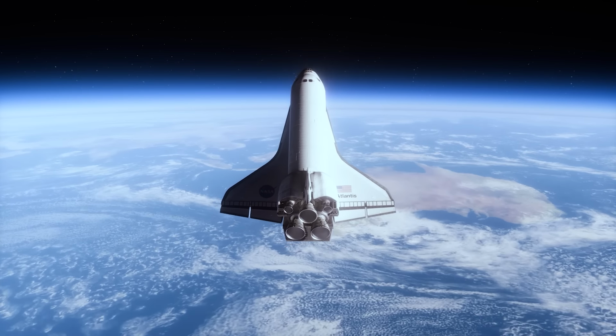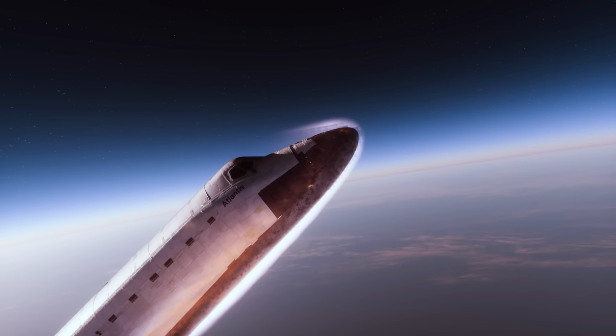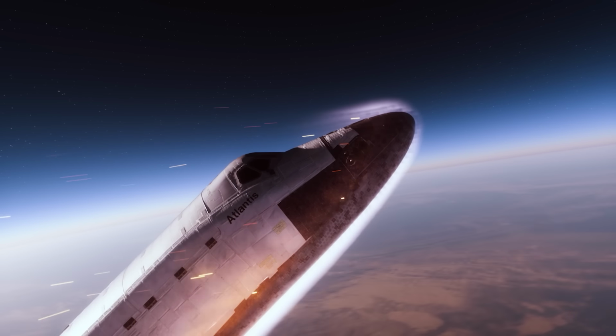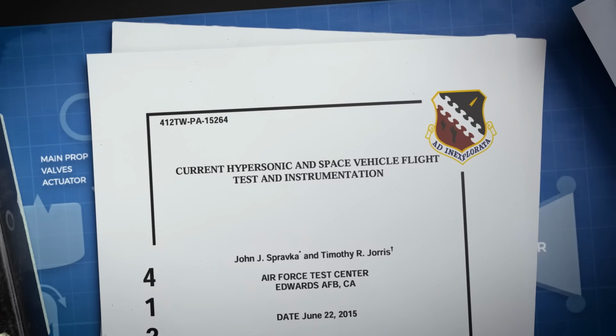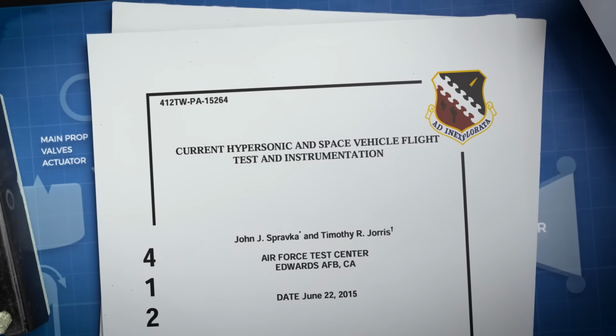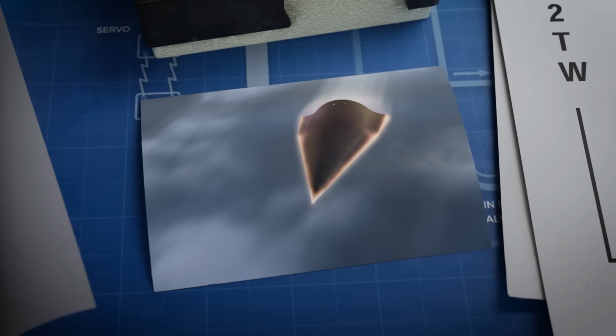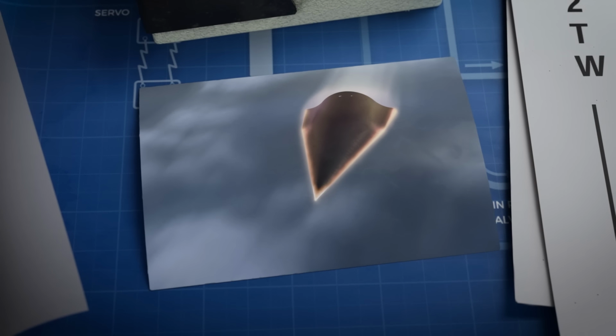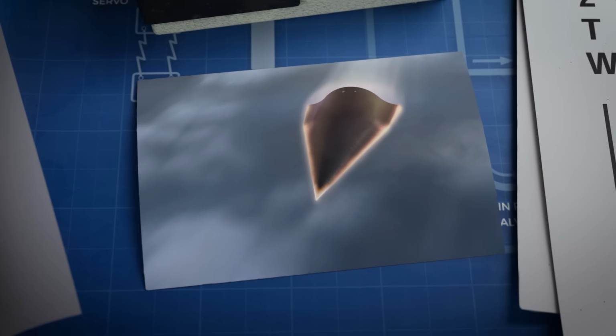This shockwave is simply a region of incredibly high pressure, and with that pressure comes incredibly high temperatures. This can have disastrous effects, as DARPA experienced twice in 2010 and 2011 when testing their sharp-nosed hypersonic re-entry vehicle, the HTV-2. Within 9 minutes of re-entering Earth's atmosphere, both vehicles disintegrated as a result of the 1,900-degree heat penetrating their metallic skin. The HTV-2 completed its mission of collecting hypersonic flight data, but the space shuttle needed to not only survive this mode of flight, but to do it repeatedly with minimal refurbishment.